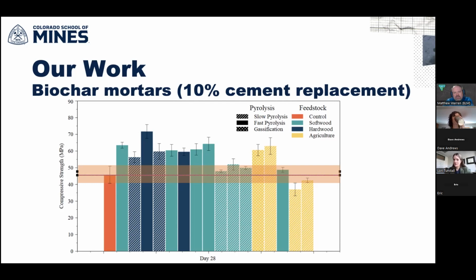Certainly that could be tested. We could look at a composite, put it under pressure and see how it behaves. We haven't had reason so far to look at that, but there are experimental methods that we could explore to see if it would degrade. I don't have any reason to believe that it would. The carbon is very stable. It's been treated at a really high temperature. We know that carbon in that form is stable under a lot of conditions. So there's no reason to believe that it would degrade, but certainly that could be part of an experimental program if that becomes relevant for that application. Okay.